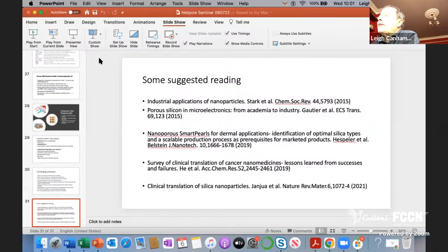Some of the lithium battery companies are looking at this. There are some bottom-up techniques. The magnesiothermic reduction technique is interesting because you start with biogenic silica, which is already a nanostructure and relatively inexpensive.